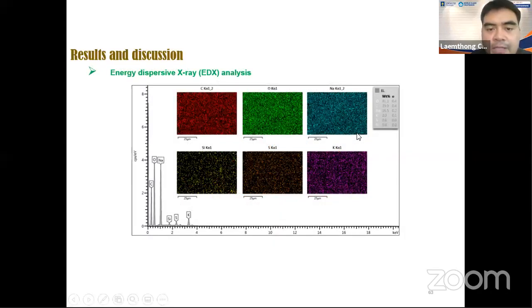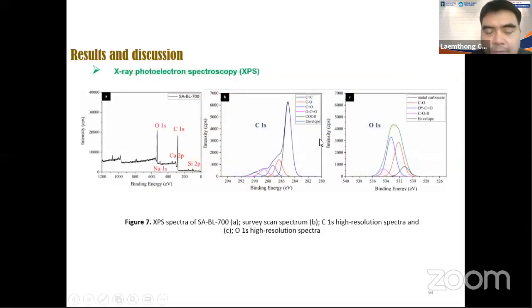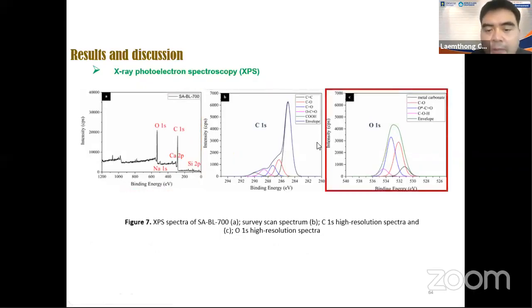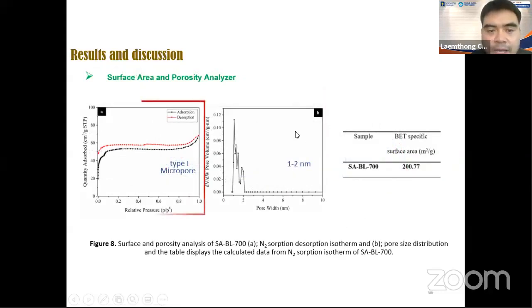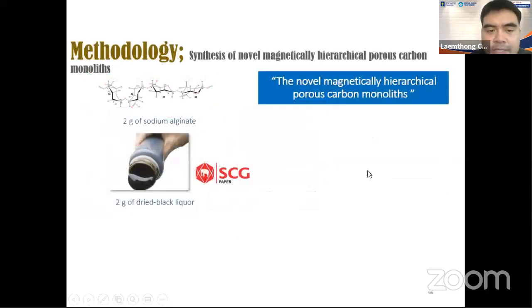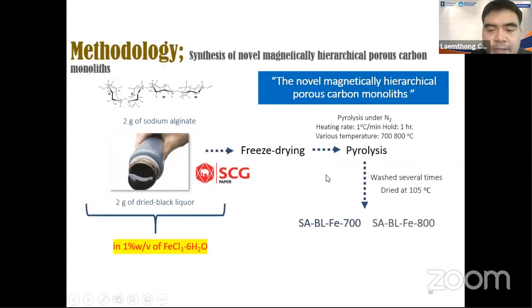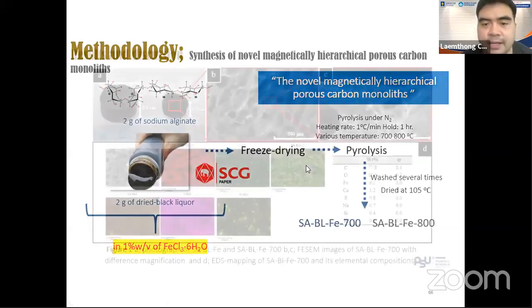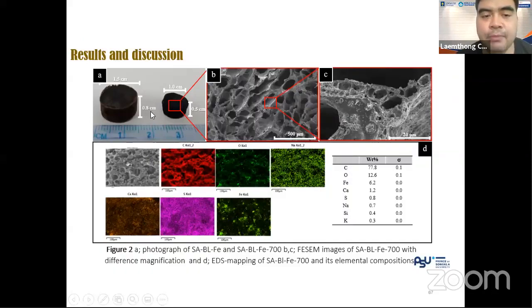We also used another technique to confirm that we still have a little bit of silica, but after washing we still have carbon, oxygen, and of course iron as well in our system. And we checked that we can have a BET surface area of around 200, which seems not so bad for this kind of monolith material. So this is the protocol: mix things together, do the freeze drying, do calcination. And afterward, we get quite a nice structure of this kind of sponge.